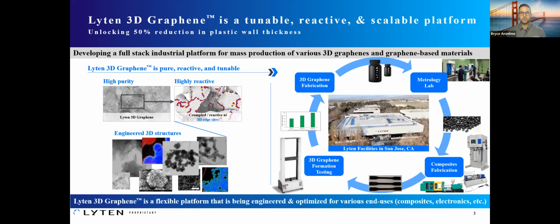I did want to point out too, a lot of the graphenes on the marketplace are actually milled down from graphite. So you're relying on your source of graphite or the ability to etch that down, whether it's mechanical, chemical, or both. And then you typically get a lot of those impurities as well as defects within those materials.